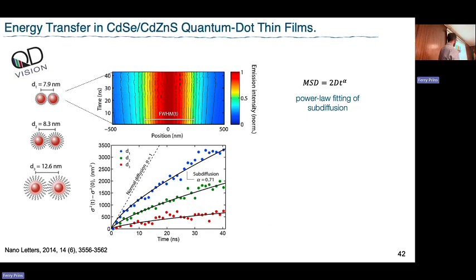As I space them out, the dipole-dipole coupling gets weaker, and my particle doesn't hop as efficiently from one particle to the next. What we're also seeing is that none of these three shows a straight line. They all show that they are slowing down as a function of time, which is an indication of disorder. So we can fit these curves in parallel, taking a parameter alpha, which tells us how fast it's slowing down.